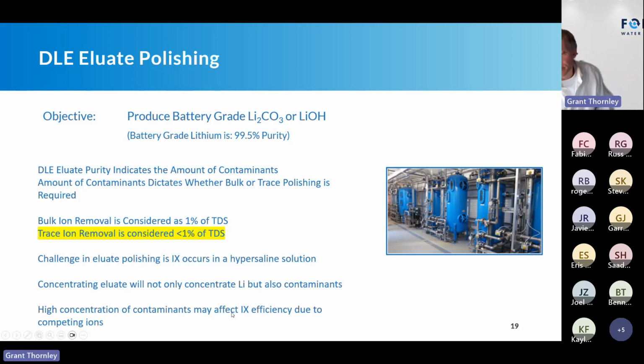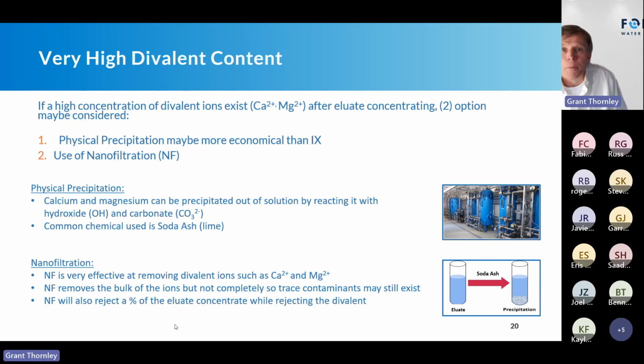The high concentration of contaminants may affect the efficiency of the competing ions, so very high divalent content. So I have my DLE eluate. I have not only my lithium, but some contaminants. Most of the contaminants you typically find are going to be calcium, magnesium. It could be potassium, some boron, and so on. But for this discussion, let's just focus on calcium and magnesium, which are divalents, after we elute. If we have a really high concentration, meaning the purity of the eluate is not that good in relationship to other DLE eluates, then we may have a bulk removal.